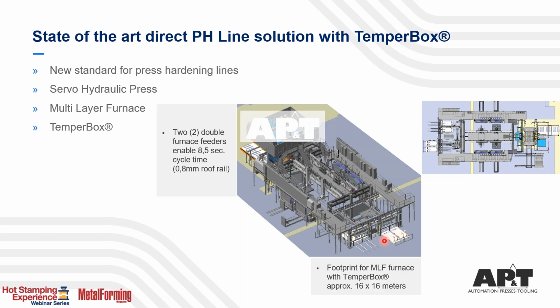A footprint of such a line is 16 by 16 meters, and this is what we have been focusing on from the very beginning since we started to use our own furnace concept: reduction of floor space, which you can also see on this type of line, that we could achieve quite a small floor space here. We have, as I said before, 4 of these multi-layer furnaces, including the temper box integrated. And if we would go back to a 1.5 millimeter thick material, we are able to reach cycle times of 12 seconds with this type of layout of our latest press hardening line.